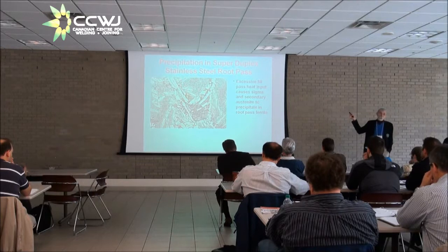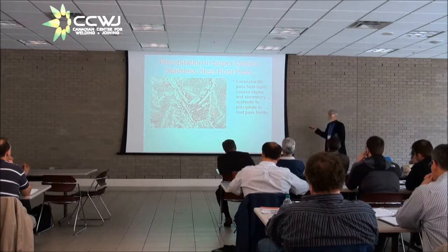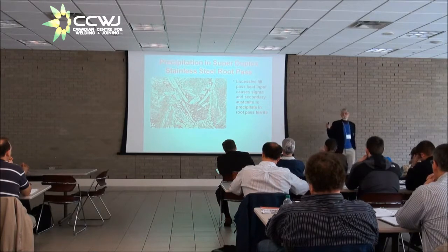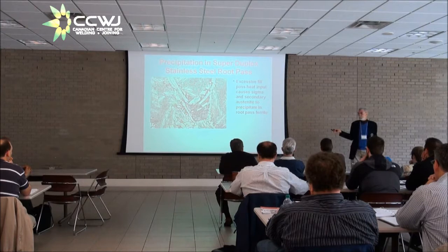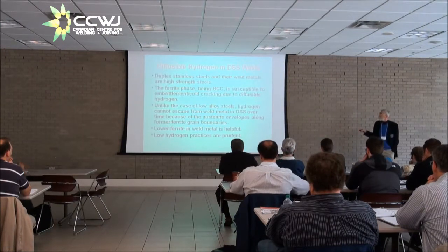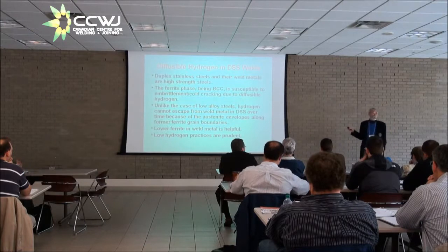You have to protect the root pass because after all, in a pipe, that's what's going to be exposed to the corrosion. And I will also tell you that if you have some intermetallics and some chromium nitrides in the interior of the material, where it's not exposed to the corrosion, if it doesn't hurt your impacts, it doesn't hurt anything. Let it be. But if it's at the surface, it's a different story. At the surface is a very different story, and it's the root pass that's at the surface.